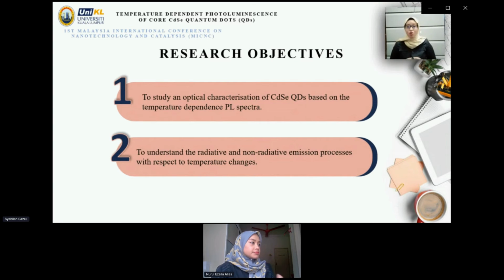Photoluminescence, or PL technique, is one of the widely used methods to investigate optical and physical behavior. This is because of its non-destructive nature. In this study, PL intensity, PL peak position, and full width at half maximum are the optical characterizations of cadmium selenide quantum dots which have been investigated at temperatures from 80 Kelvin to 300 Kelvin. By measuring the PL spectra based on temperature dependence, it allows us to study the radiative and non-radiative emission processes.